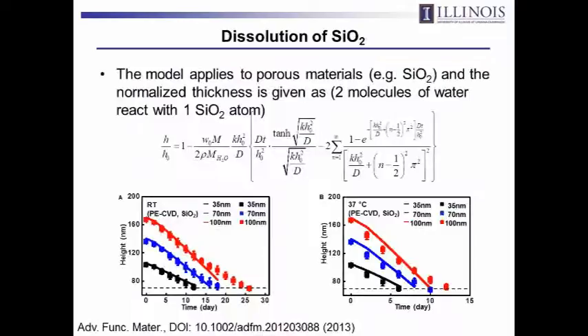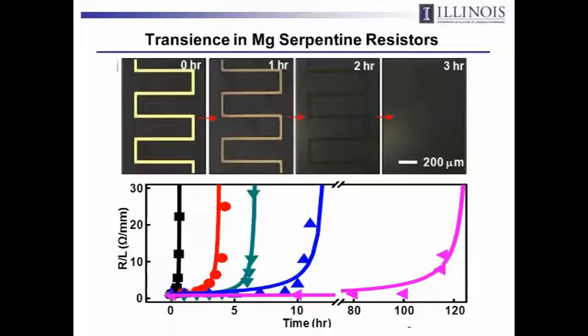So that's the strategy for building in well-defined lifetime in an overall system that will nevertheless eventually disappear. From an engineering standpoint, you need to know exactly the kinetics of how things are dissolving so that you can design the system to behave in the way that you want it to behave. So a lot of what we do is look at how quickly different materials are dissolving, modeling that rate of dissolution with analytical models so that we can use those as engineering tools to do the system design.